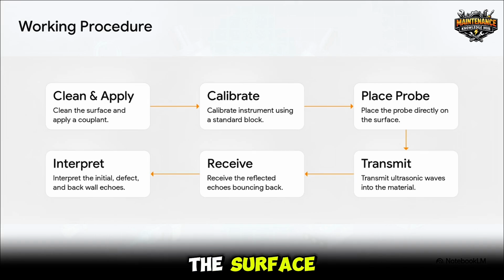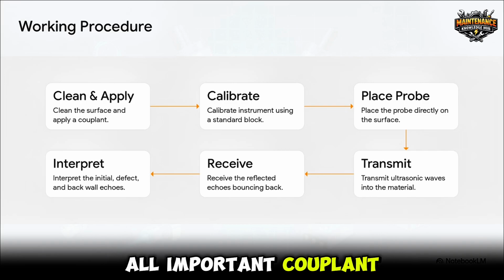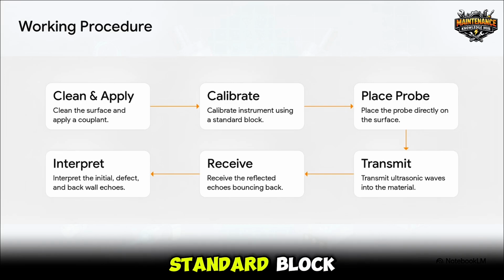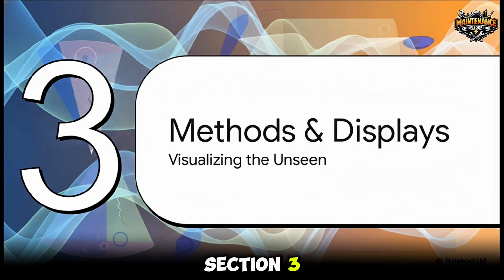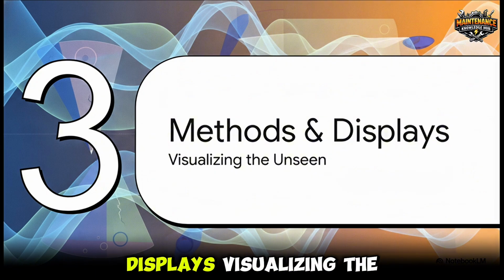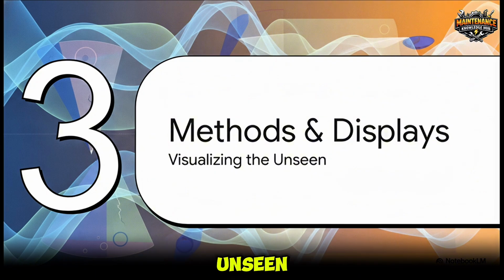In practice, an inspection follows a really strict step-by-step rhythm. First, the operator cleans the surface and applies that all-important couplant. Next, they calibrate the instrument using a standard block, like an IIW V1 or step block. Then, they place the probe flat against the material, transmit the ultrasonic waves inward, and wait to receive the bouncing echoes. When they interpret the display, they'll typically see an initial pulse where the sound entered, a backwall echo from the far side of the material, and, if there happens to be a problem, a defect echo popping up right in the middle.